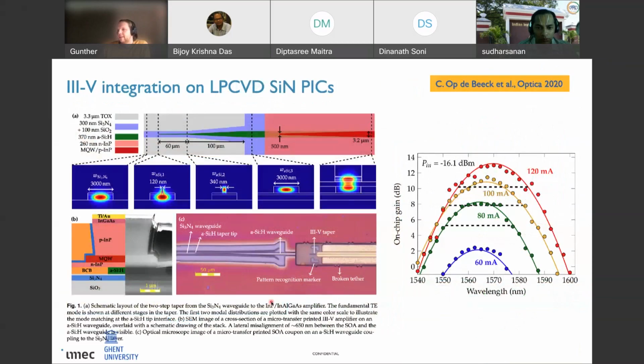So something similar was then done on silicon nitride waveguides, as I said, using an amorphous silicon interlayer. So we have a two-layer taper, which first transitions, let's look at it from this side, from the III-V on silicon mode to an amorphous silicon waveguide mode, and then into the silicon nitride. So here we also got similar performance, about 10 dB of gain for 100 milliamps of drive current.